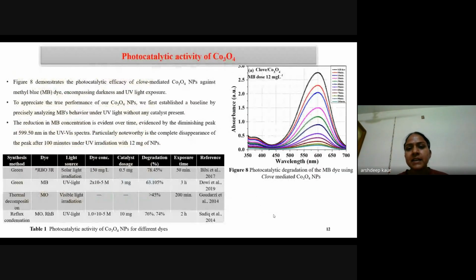For the photocatalytic activity, we have used methyl blue dye. For the degradation of methyl blue dye, we have used a catalyst amount of 12 mg. As we can see from the figure, the diminishing peak at 599 nanometers shows complete disappearance after 100 minutes under UV irradiation with 12 mg of nanoparticles.